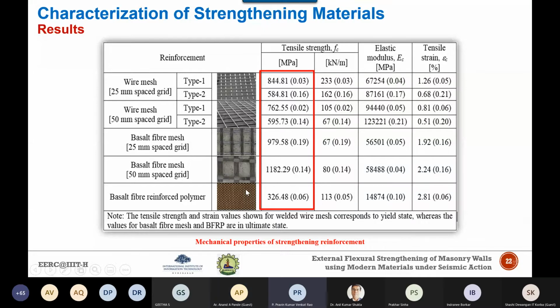In the present study, the tensile strength of the welded wire mesh is observed in the range between 580 to 850 megapascal, whereas for basalt fiber mesh, the strength comes out to be in the order of 900 to 1200 MPa, and for the fiber reinforced polymer, the strength comes out to be 326 MPa. So these are all the test results of the dry fiber mesh, not of the composite. Now let's see the composite specimens.